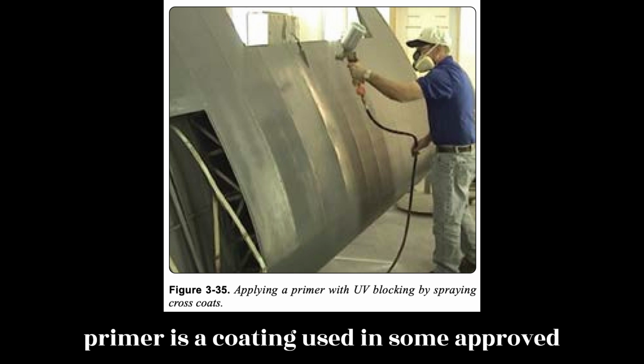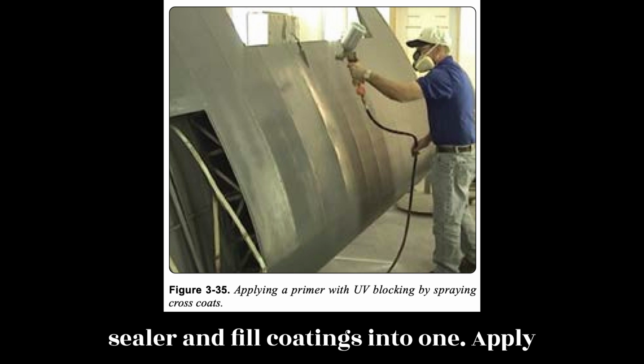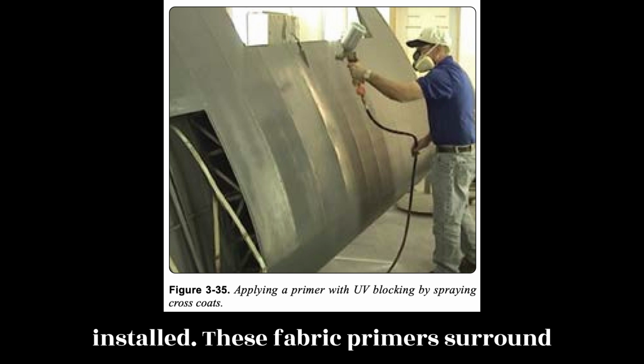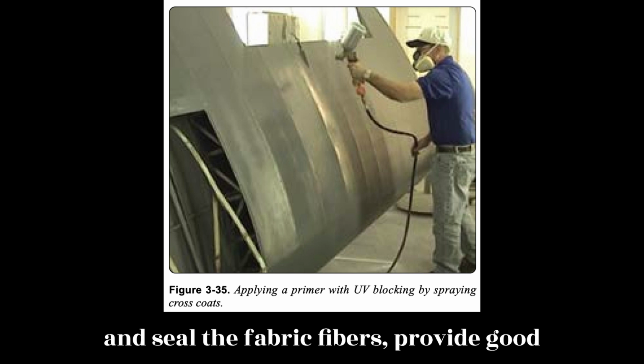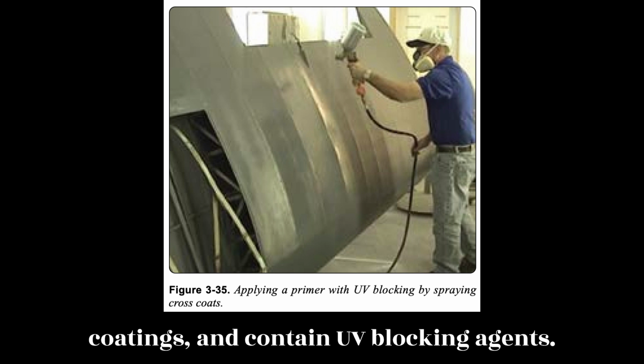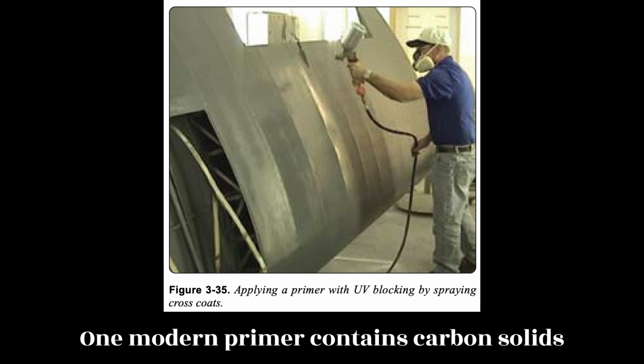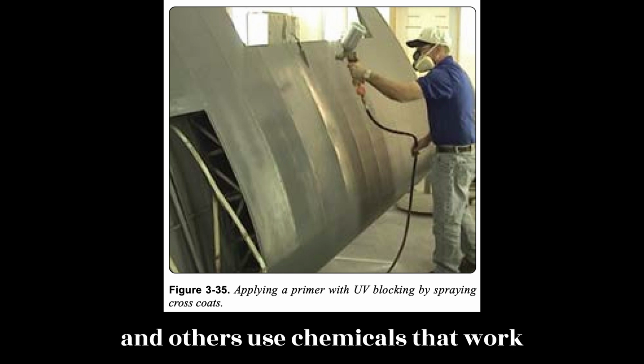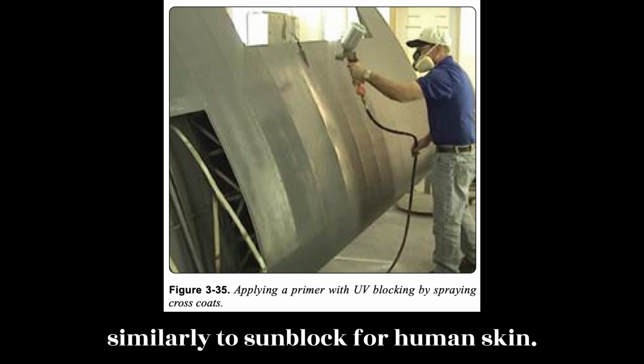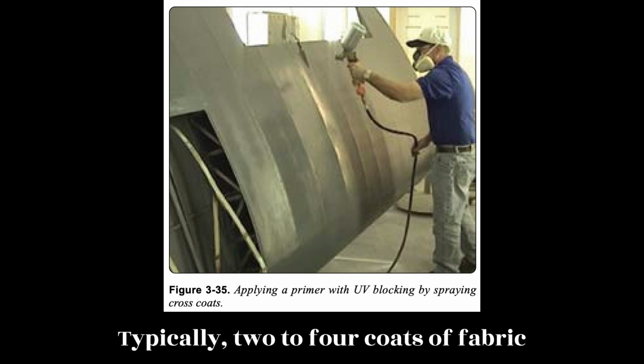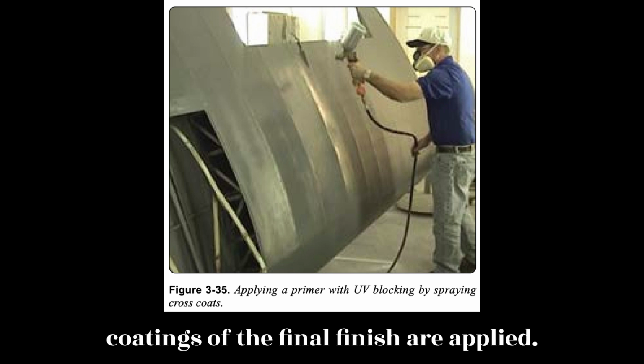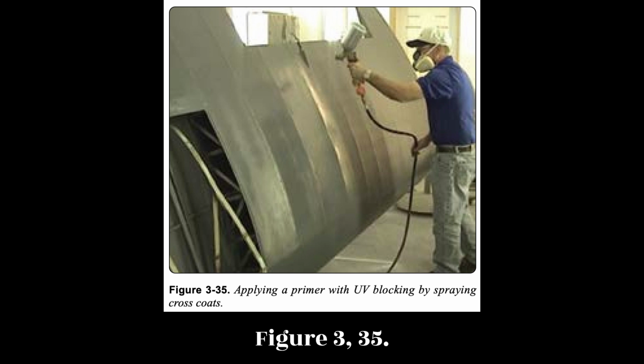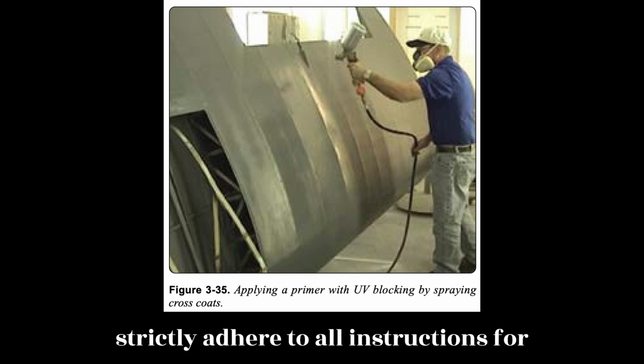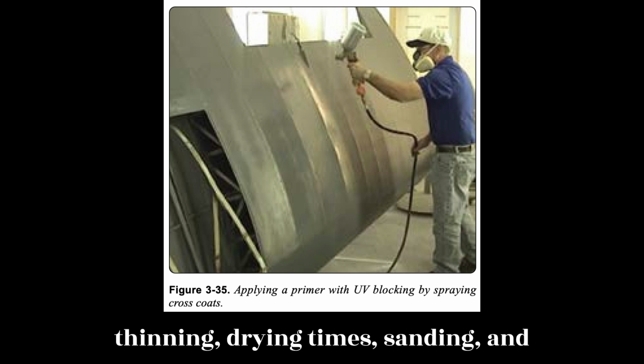Fabric primer is a coating used in some approved covering processes that combines the sealer and fill coatings into one. Applied to fabric after the finishing tapes are installed, these fabric primers surround and seal the fabric fibers, provide good adhesion for all of the following coatings, and contain UV blocking agents. One modern primer contains carbon solids and others use chemicals that work similarly to sunblock for human skin. Typically, 2 to 4 coats of fabric primer are sufficient before the top coatings of the final finish are applied. Figure 3.35. The FAA certificated mechanic must strictly adhere to all instructions for thinning, drying times, sanding, and cleaning.